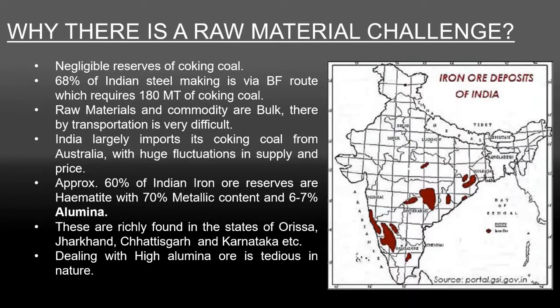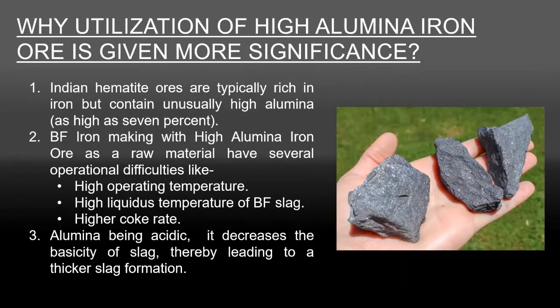Dealing with high alumina ore is tedious in nature. Utilization of high alumina iron ore is given more significance. Indian hematite ores are typically rich in iron, but they contain high alumina. Blast furnace iron making with high alumina iron ore has operational difficulties like high operating temperature, high liquidus temperature of blast furnace slag, and higher coke rate. Alumina being acidic, it decreases the basicity of the slag, thereby leading to a thicker slag formation.